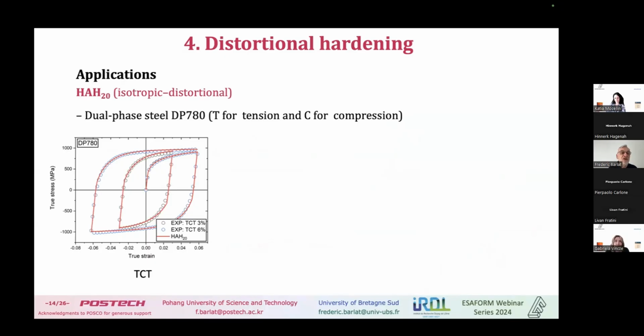And we have several versions of what we call the HAH model. This is the isotropic distortional model on a dual phase steel. We know T for tension and C for compression, and this one is TCT, meaning tension, compression, tension. So we have two curves here with different amplitude for the change, one with a small amplitude, and the second one with a bigger amplitude. Around the circle are the experiments. The red line is the model, and it works well.